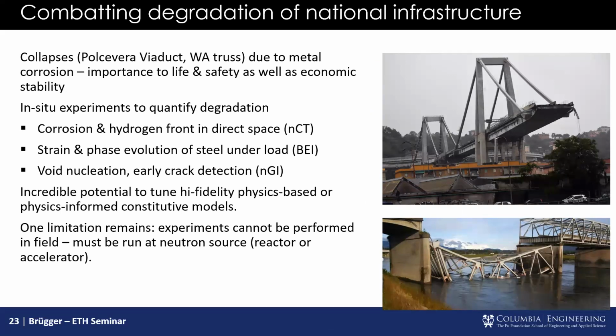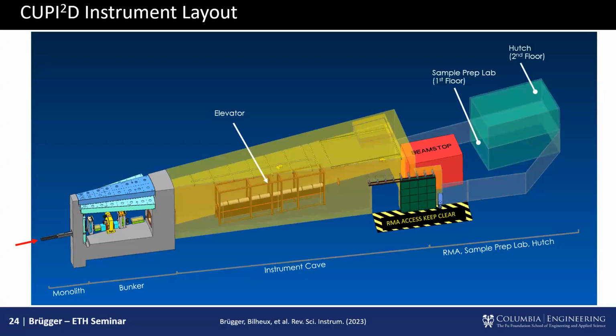We cannot do this in the field, but if we have a sample, for example, we can look at hydrogen embrittlement. We can actually map the hydrogen front. We can also look at strain and phase evolution as well as corrosion products as they infiltrate the steel substrate. And of course, early crack detection. So this still is quite powerful.